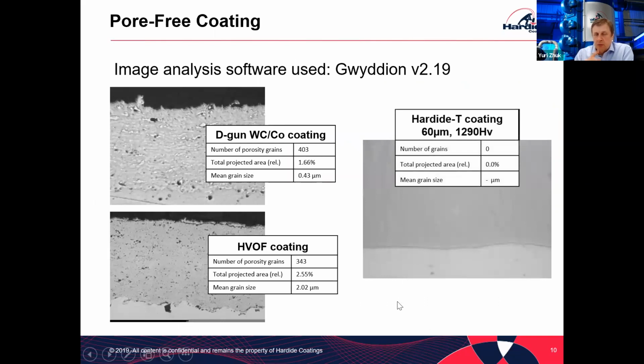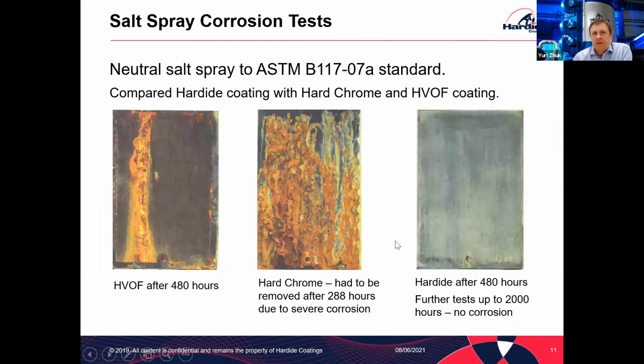The coating that we produce is pore-free. So this illustrates the measurement method of porosity. And because of very, very low porosity, it can be a very good barrier against corrosion. So what is shown on this slide is 3 different coatings, HVOF on the left, hard chrome at the center, and Hardide on the right after salt spray corrosion testing.